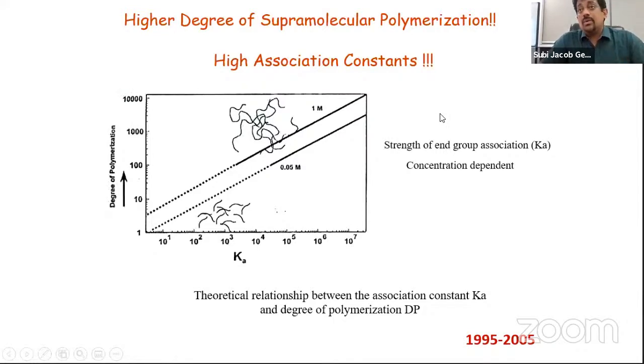This is a big realization, because if you want to use phthalic acid and make supramolecular polymers, the association constant of benzoic acid or acid groups will be somewhere here, 10 to the power 2. So you cannot make polymers. If you try to make this kind of material with acid groups, most probably you will get a degree of polymerization of about 10, which is not a polymer. Even for a DNA base pair, the association constant is something like 10 to the power 3, and you may not get more than 100 or 150 monomers in a polymer chain. So that was the initial challenge.